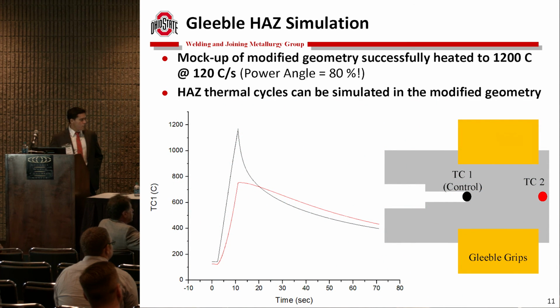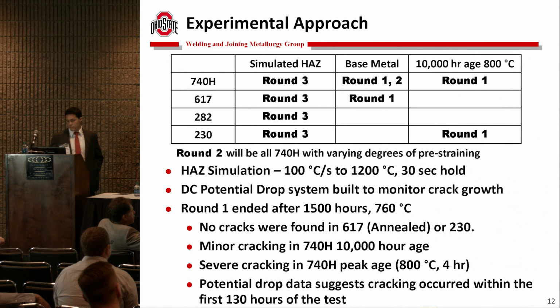So another advantage of making the sample so thin, 40% of the original thickness, is that now I can fit it in the Gleeble. And so that's great because I can make virtually any microstructure I want in this area, which I'm going to yield and subsequently creep test. So the big picture game plan for me, or the ultimate goal, is to test the creep relaxation cracking response of simulated heat affected zones. But of course there are a couple rounds of testing before we get there.